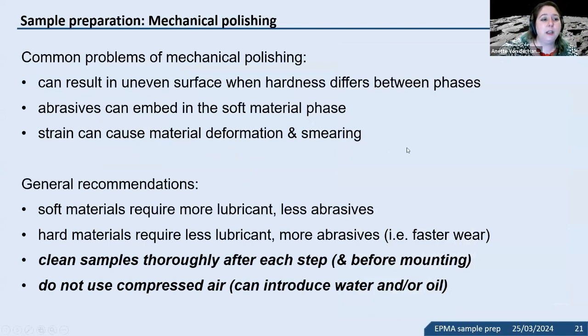Common problems of mechanical polishing are that, again, you get uneven surfaces. We don't want that. If we have a multi-phase material where the hardness really differs, then sometimes it can also be a real problem that abrasive can be embedded in soft materials, usually alteration phases. I can't tell you how many times we were like, oh, diamonds during an analysis, and then it turns out that all the diamonds are exactly 9 micron in size, and obviously, even in a thin section, just like contamination from polishing.